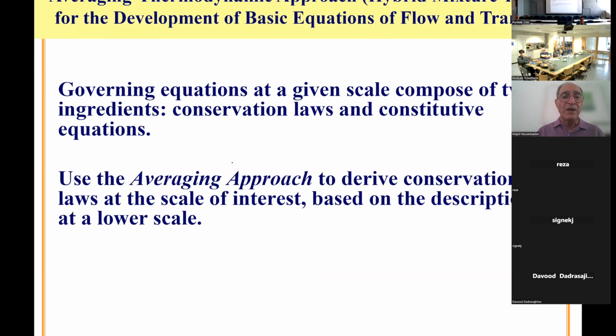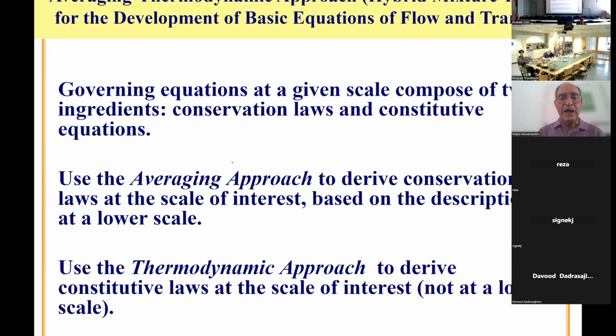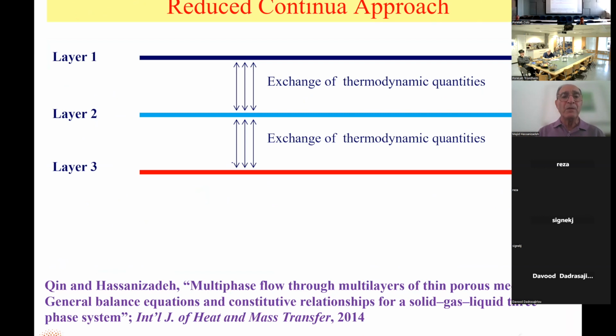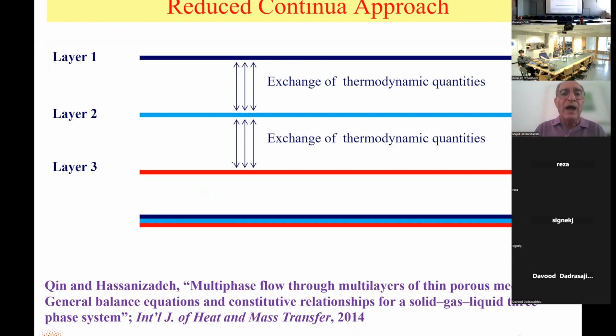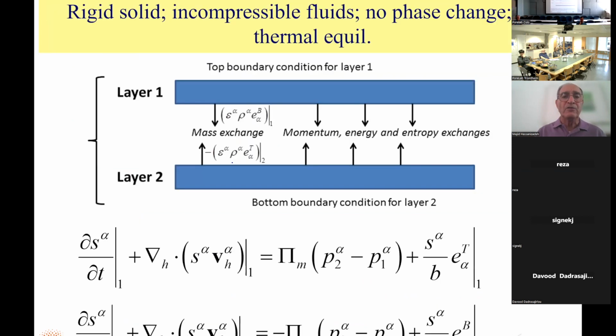So this means that we derive equations of conservation first, then we use the rational thermodynamics in order to obtain constitutive equations. I'm not going to go through that, but the three layers that are very thin layers with some thickness, they are modeled at the macro scale as zero thickness domains. So they are zero thickness and they only have an order with respect to each other. One is on top, one is in the middle, one is bottom, and they exchange thermodynamic quantities with each other.